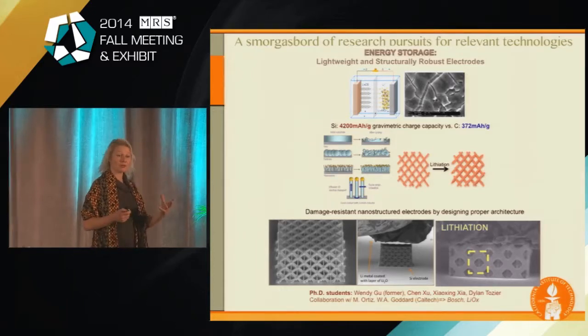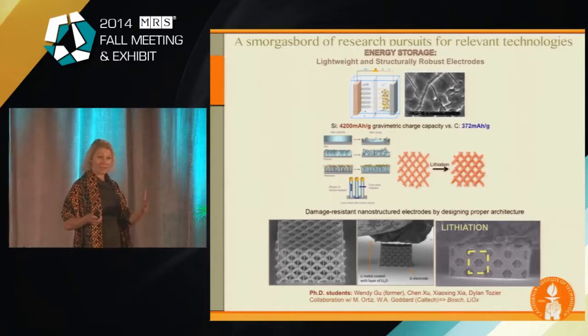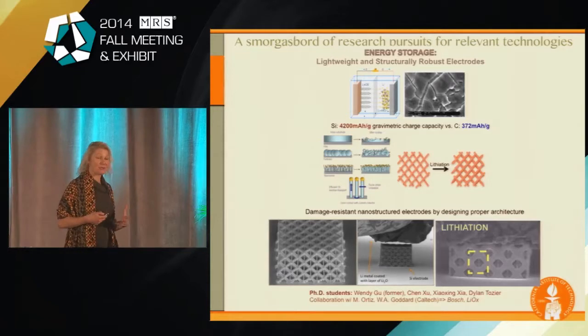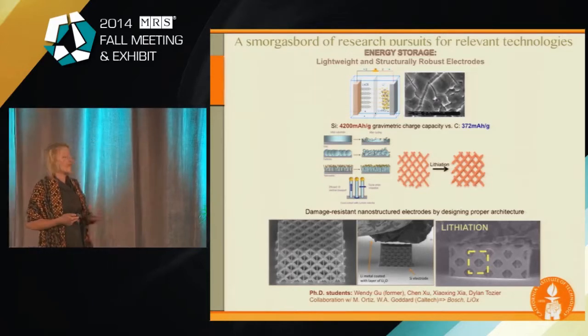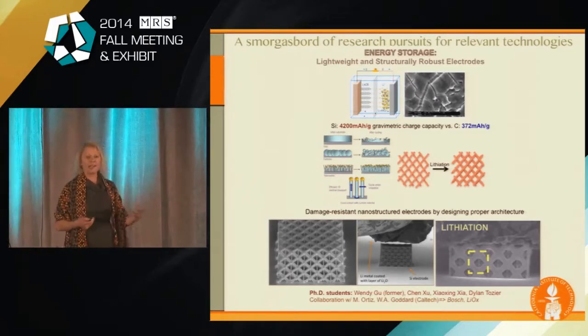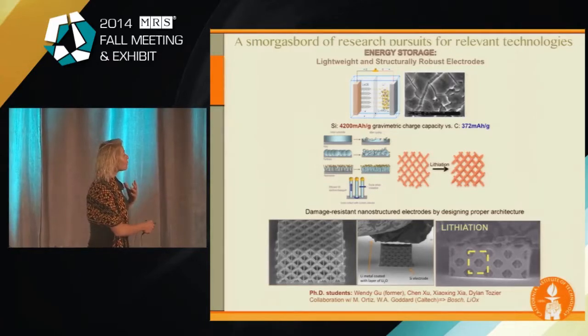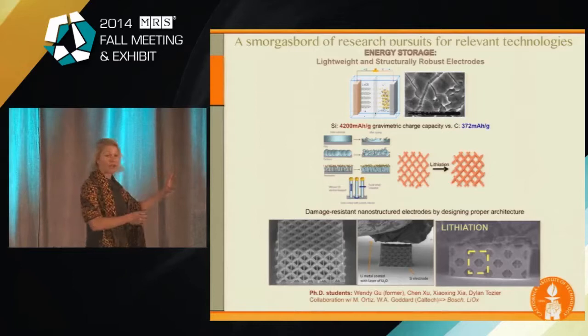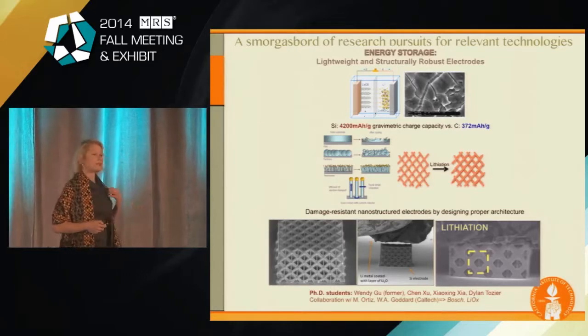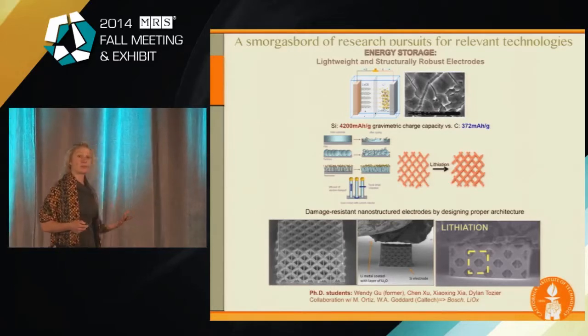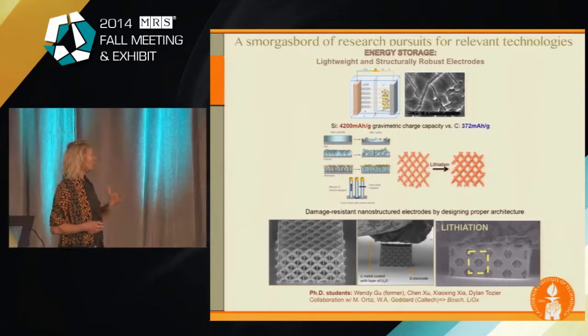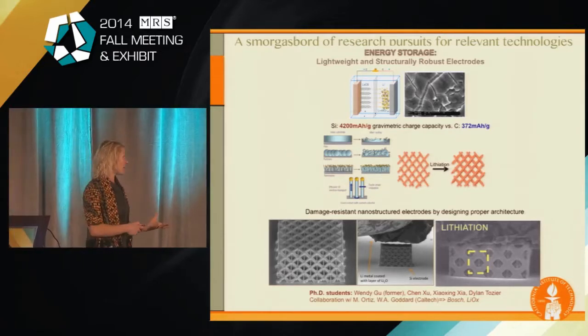So what happens upon lithiation is that the lithium ions go inside the anodic material, and it swells up. And if this material happens to be a brittle ceramic like silicon, it would undergo a volumetric expansion of about 400%, and it just can't stay intact, and so it'll fracture. It's too much of a hydrostatic stress state, stress triaxiality, which would drive the fracture, and the fracture would propagate everywhere. And so this is one of the many reasons why silicon, even though it's so much better for the storage capacity, is not being inserted into the commercial lithium-ion batteries.